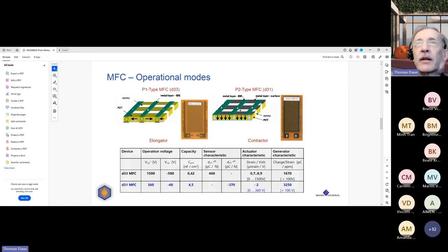Also, due to the higher coverage of electrode material, a typical D31 MFC for energy harvesting gives you about 3,250 picocoulomb per ppm charge output. As you know, the MFC is not delivering a voltage. It's a current, often overlooked, but you're dealing with AC current coming out from a PZT harvester. Compared to the same size D33 MFC, which is only half as much. So that's why we developed the P2 type MFCs, to get higher output.